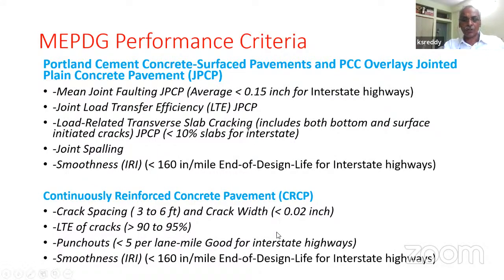Similarly, if it is a continuously reinforced concrete, you have got similar parameters. What I'm trying to say is the mechanistic empirical pavement design guide, MEPDG, talks in terms of cracks, talks in terms of foundation erosion, talks in terms of the spalling that occurs near the joints, the faulting that occurs near the joint. It talks in terms of those physical problems which you can see and measure and quantify, and it sets limits on those. But in India, the current guidelines are only in terms of roughness. They also have criteria in terms of roughness, but they do not have criteria for more important distresses, structural distresses, which you can control in our design process.